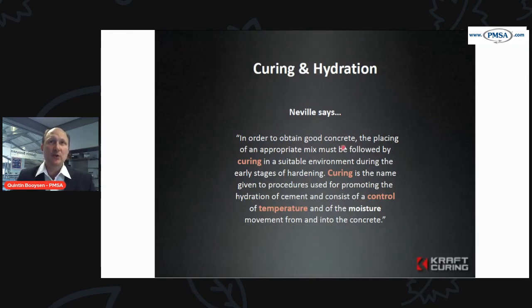In order to obtain good concrete, the placing of an appropriate mix must be followed by curing in a suitable environment during the early stages of hardening. Now, those early stages, we are talking about from the setting of concrete right through to that first 24 hours. That is critical. Curing is the name given to the procedures used for the promoting of the hydration of cement, and consists of a control of temperature and the moisture movement from and into the concrete.